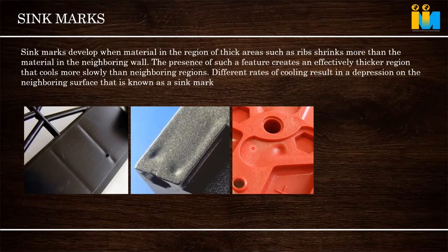So we have to provide proper cooling lines. In this spot, some cooling line, a spot element. If it is not at all going, some people give higher temperature steel in the area, like beryllium copper. They will put a small piece of beryllium copper in this sink mark area so that it quickly conducts the heat.